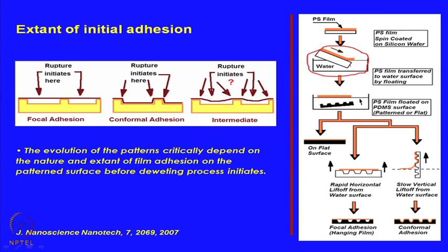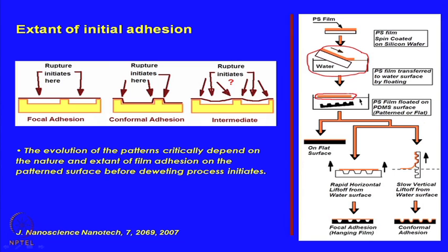This is a very tricky experimental protocol where you hold through the edge and the film detaches completely from the substrate on which you have coated it. You now have a freely floating film on the surface of this liquid, which you have to recapture with a topographically patterned substrate. This is difficult, but it can be done.